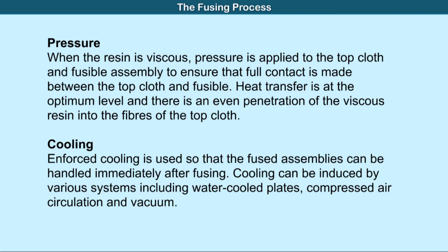Next is the pressure. When the resin is viscous, pressure is applied to the top cloth and fusible assembly to ensure that full contact is made between the top cloth and fusible, heat transfer is at the optimum level, and there is an even penetration of viscous resin into the fibers of the top cloth.